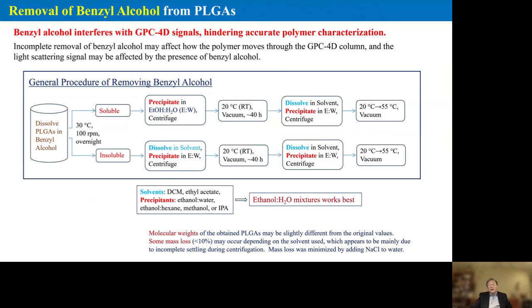After several trials, we found out that once we dissolve the PLGA sample in benzyl alcohol, for example, we separate the soluble fraction and insoluble fraction, and then go through precipitation, dissolution, precipitation again. That process, at least twice, removes most of the benzyl alcohol to a negligible level. So the best precipitant we found was an ethanol-water mixture, 1-to-1 ratio.